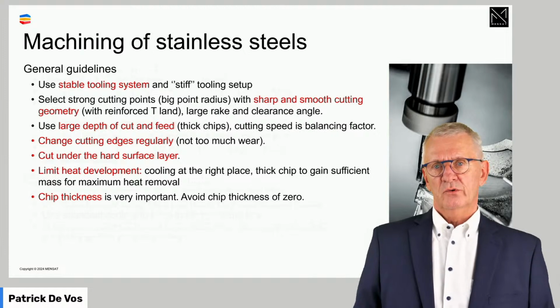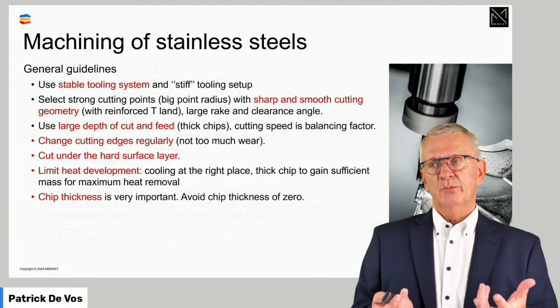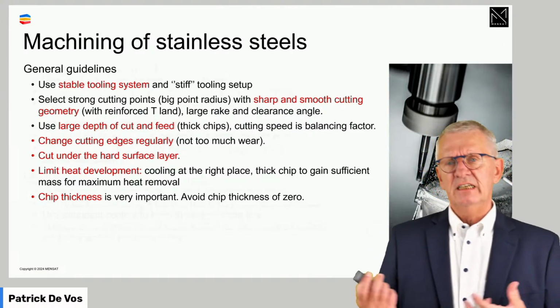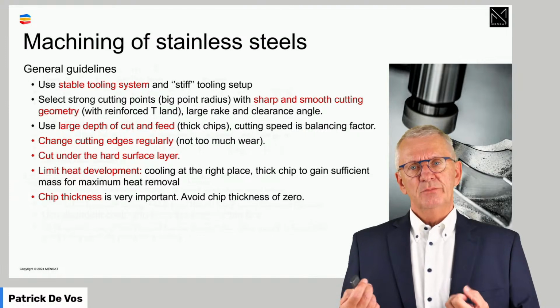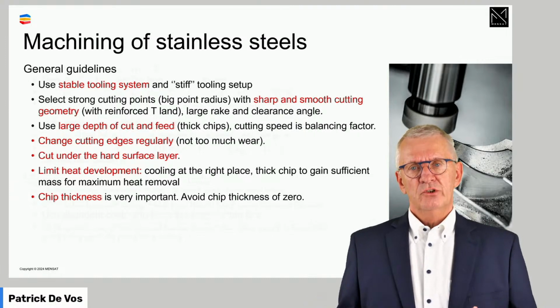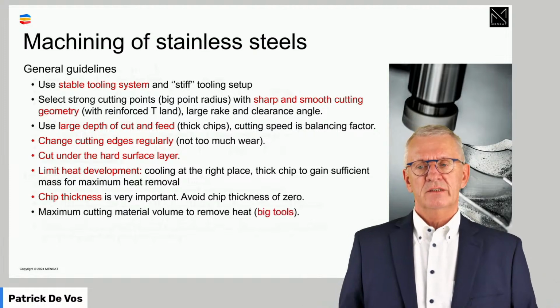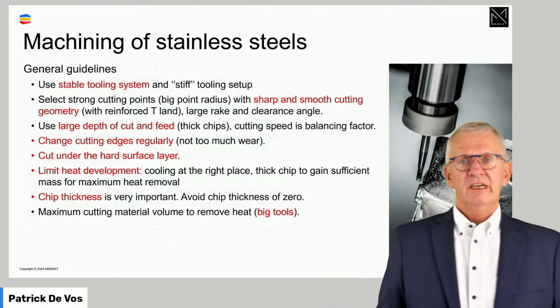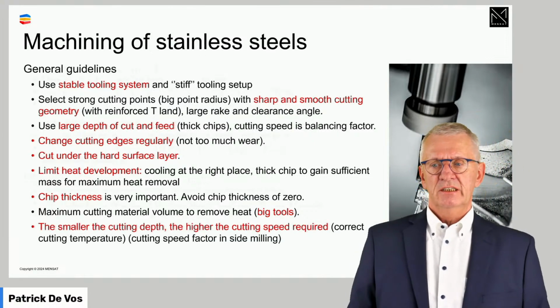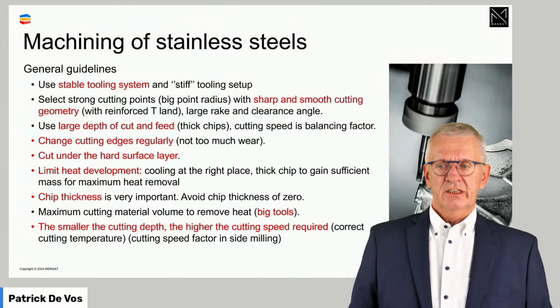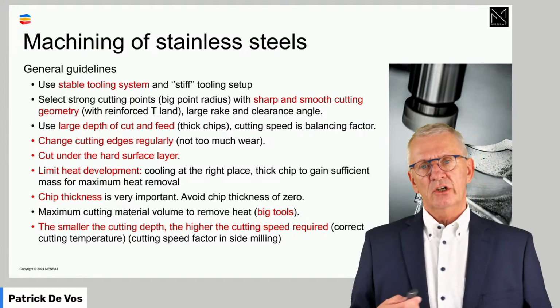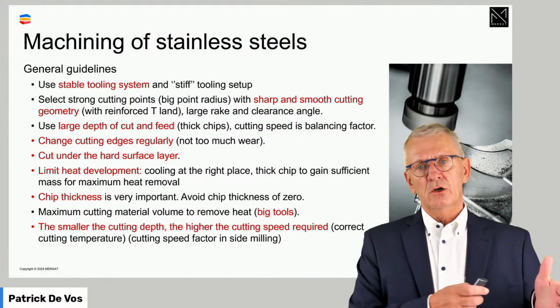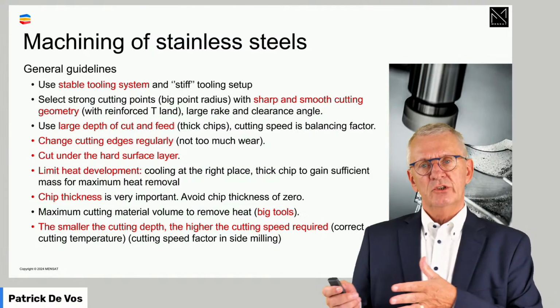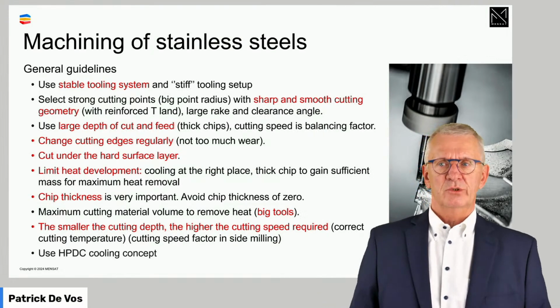Chip thickness is very important. The thickness of the chip, because the thicker the chip, the more capacity it has to evacuate heat out of the cutting zone. Thin chips don't have that. That would make the problem with too high temperatures in the cutting zone even worse. Use big tools, have a big mass to evacuate heat. If you reduce your cutting depths, then you should increase your cutting speeds. Remember, it's not about low temperatures, it's not about high temperatures, it's about avoiding some critical temperatures.